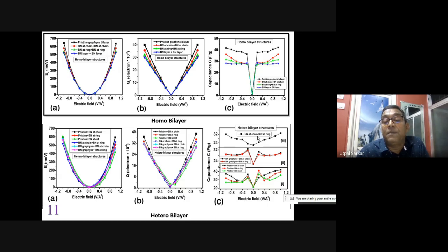One interesting thing happens here for heterobilayer. These structures are not basically symmetric, because one layer has different properties than the other layer. Depending upon the electric field, some residual amount of charge can already reside there, and the electric field has to overcome or minimize that effect. That is presented here, and that is why it is not symmetric. Otherwise, the nature of the two is basically the same.